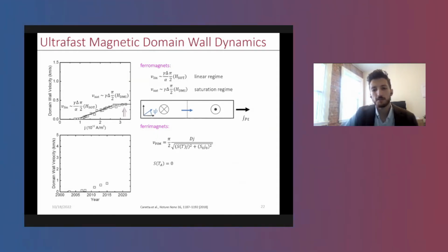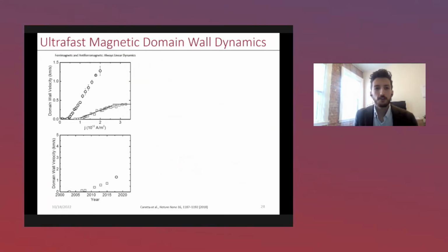If you have a system that's completely compensated, meaning that it has no net spin, what you'll find is that the equations of motion for this domain wall change quite dramatically. So instead of having a linear regime and a saturation regime, in fact, you just have a linear regime. The velocity is always proportional to the current. You always get linear dynamics. And in fact, we proved this. So using a completely compensated gadolinium cobalt system, we've achieved purely linear dynamics.